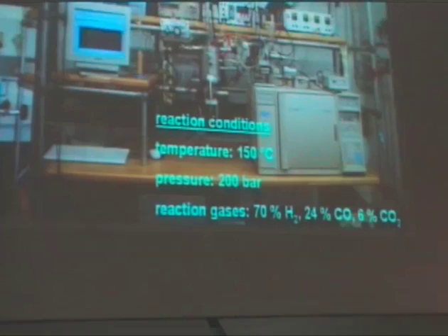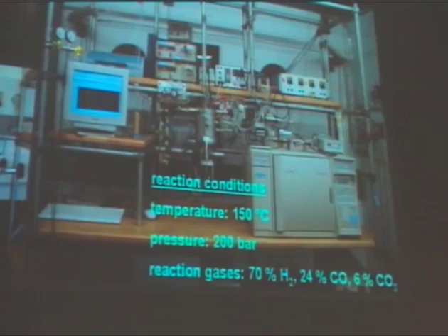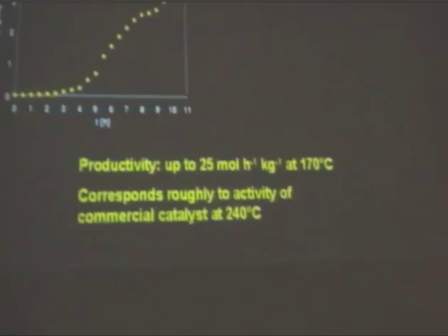Typically, we ran reactions at 150 centigrade, 200 bar, but we went up to 200 centigrade and appreciably above 200 bar. This is not the typical syngas composition you have in the gas phase, because you have to take into account the solubility of the gases in THF to come to roughly identical conditions as in the gas phase. And if you do the reaction, you indeed see that these copper nanoparticles produce methanol.